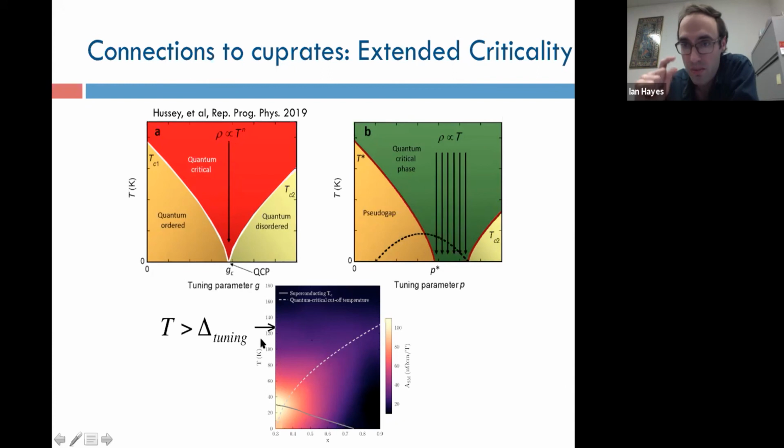You can see the main detuning energy, which gives you this fan-like region and some region of doping independence in the Hall response. Then there's some other energy or time scale that makes those fluctuations, or the effect of those fluctuations in the transport, non-zero all the way down to zero temperature. There's something that sustains the effect throughout this region. So that'll be an important avenue to consider in the future.